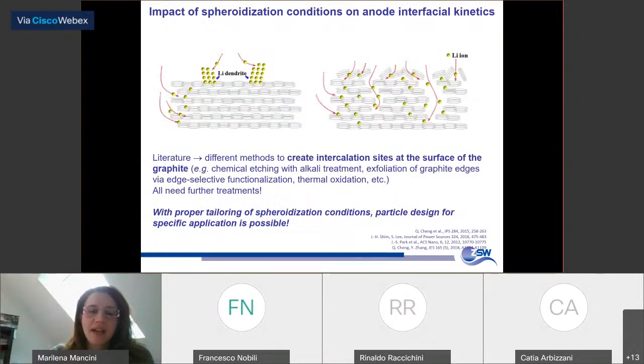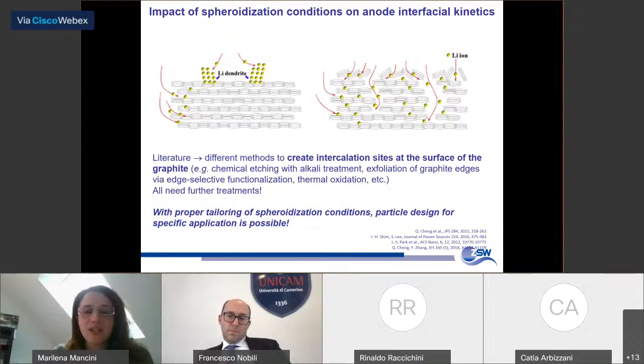What we think is that with a better understanding of the process parameters, which depend really much on the machine and the method used, we can tailor the surface properties to offer sites for faster lithium intercalation. And I took this picture from literature, and it is a nice example of what I mean. So when we don't have nice surfaces open to intercalation, the lithium accumulates on the surface and eventually leads to lithium dendrite and lithium deposition. But when properly tailoring the surface properties, then we can intercalate the lithium faster. There are different examples in literature, but they all require some treatment like oxidation or exfoliation or other treatments, while the same result can be obtained by monitoring the spheroidization.